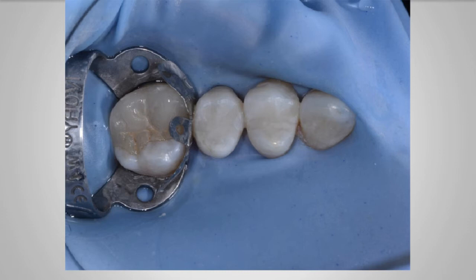And when you see that kind of white line forming, it usually means you placed too large of an increment and maybe you connected it to the other side, and when you cured, it shrunk and pulled, and it creates a little micro gap. So one of the things you'll notice when you start curing one side at a time, or one cusp at a time, or buccal and lingual cusp, you might say, you're going to see less of those white lines form, and that's really nice. It's a great feeling because you're doing a better job.